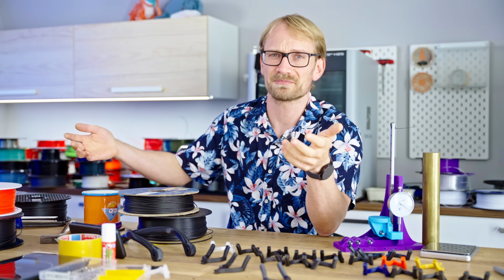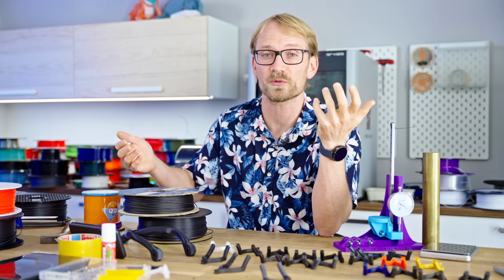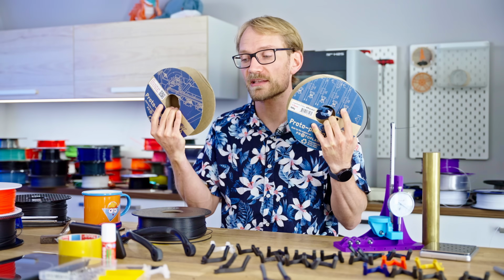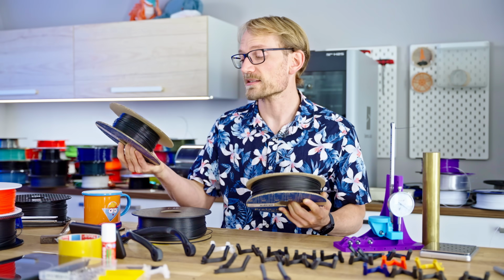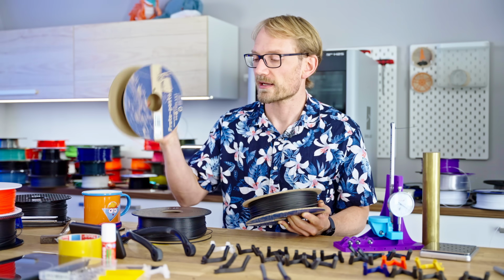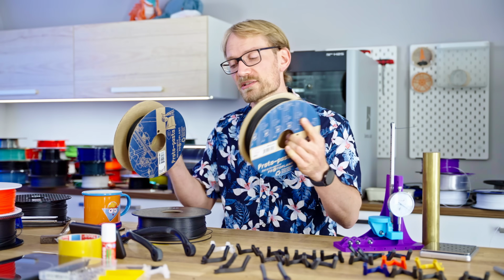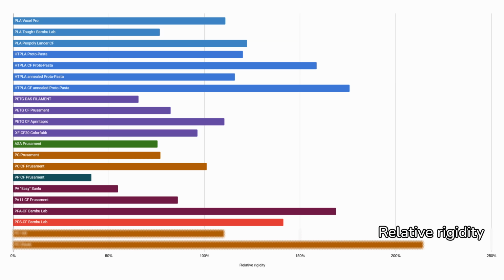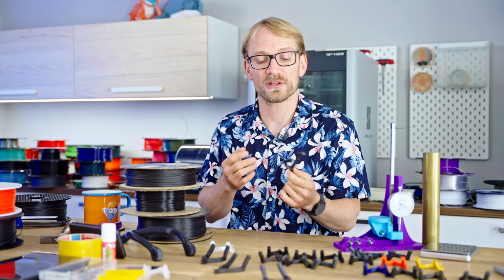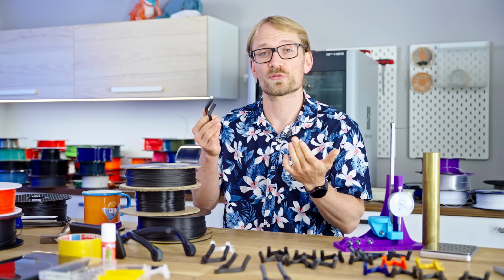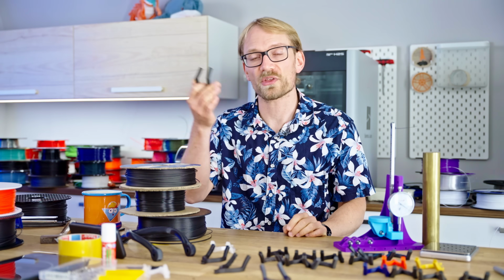These parts were printed and tested within 48 hours of being printed. So I can also look at how much rigidity the two HTPLAs gained. These are different generations of HTPLA between the plain and the carbon fiber ones, so they do behave a little differently. The plain HTPLA, within margin of error, actually gained no rigidity at all. And the carbon fiber HTPLA from heat treating gained about 10% rigidity with minimal shrinkage, warpage. So that is something that I think is definitely worth it. And again, it produces the most rigid parts out of all of these with that extra heat treating step.